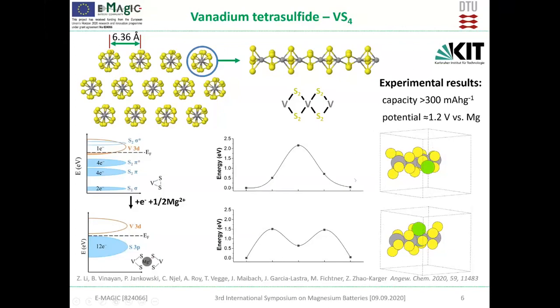Okay, so you can see that thanks to the structure, the energetic barrier is lower. You can see that the energetic barrier is still high for this case, but we are doing calculation just for one magnesium in the structure. So if you want to see what really is happening in the material, we need to look at what is happening when we are charging the material completely.